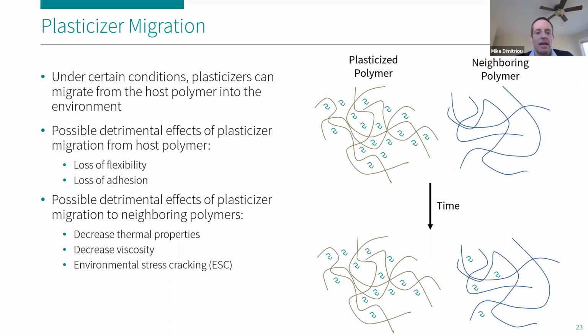And unfortunately, this has a double negative effect. You get a change in properties of the host polymer that is losing plasticizer, and you also get a change in properties of the neighboring polymer that is gaining plasticizer. The host polymer, by losing plasticizer, may demonstrate a loss of flexibility and or a loss of adhesion, while the neighboring polymer, which was originally made to not be flexible or not contain plasticizer, is now possibly experiencing a reduction in viscosity, may be susceptible to environmental stress cracking, and may be becoming more flexible than originally intended.